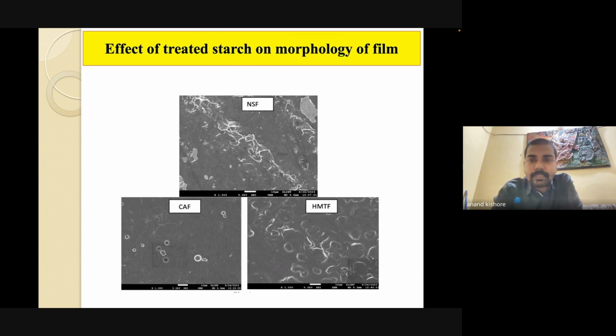Next, in the same analysis, we found that the surface of the film is very rough in the case of native starch, but in the case of citric acid and the HMT treatment, the surface is very homogeneous and the structure is regular. So it may be that this affects the properties of the film, and there is an improvement, we can say, in the properties of the film.